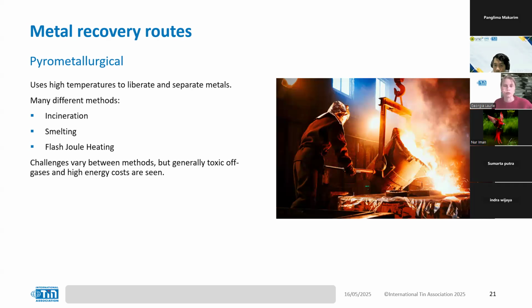This rapid Joule heating drives off organic components and vaporizes many metals, and then those metals resolidify as fine particles or condense on the reactor walls. So we get a metal-enriched residue that we can then leach for metal recovery. This method is being trialed commercially by an Australian company, MTM Critical Metals. Importantly, flash Joule heating is far less energy intensive than conventional furnace smelting.